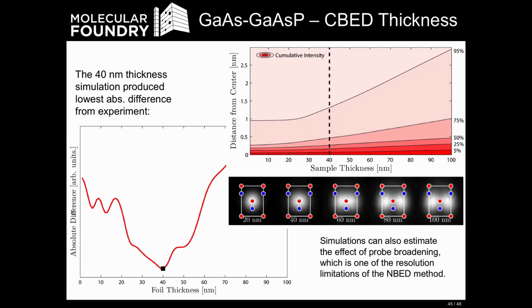We also wanted to sort of estimate our resolution. Now that we know our sample is 40 nanometers thick, we can look at our distance from the center of the probe, the sort of spread of the probe. I plotted the cumulative intensity here, and we can see, for example, that 75% of our probe is inside about 0.5 nanometers at a thickness of 40 nanometers. And this is all from the simulation.